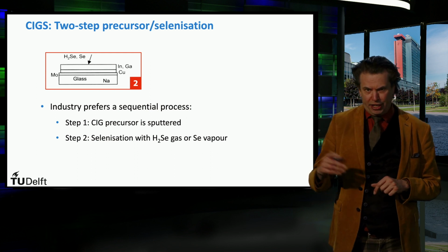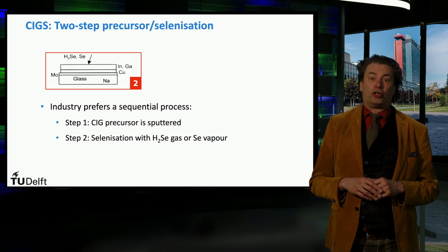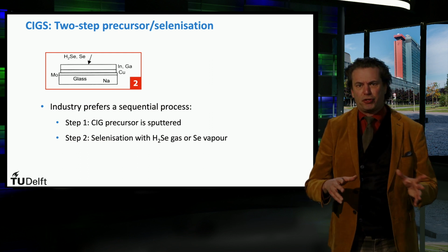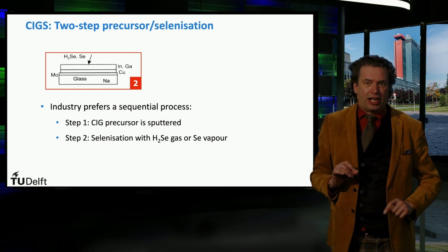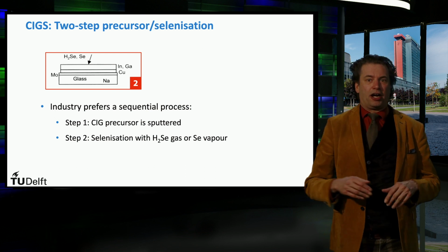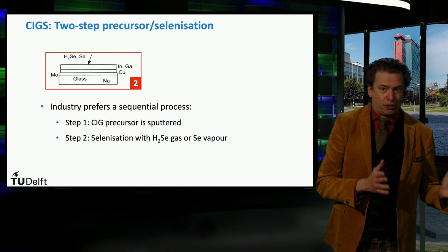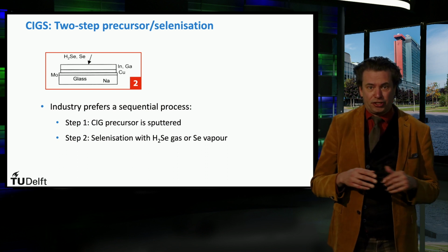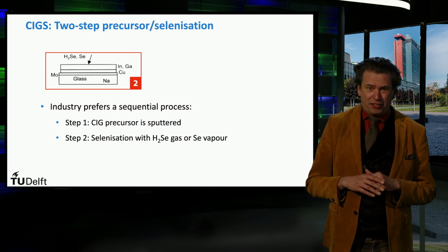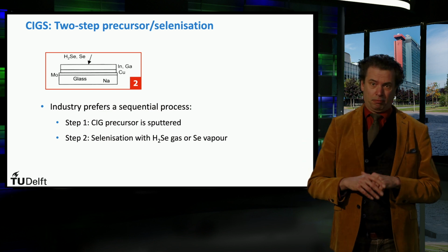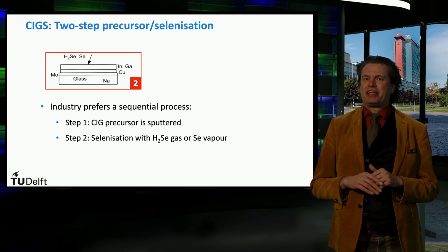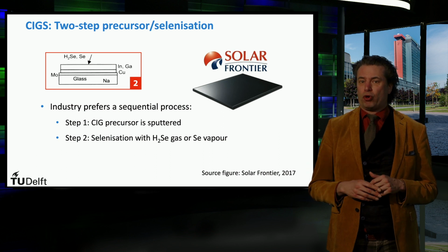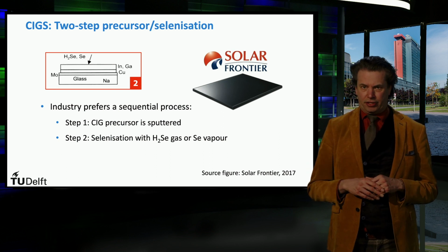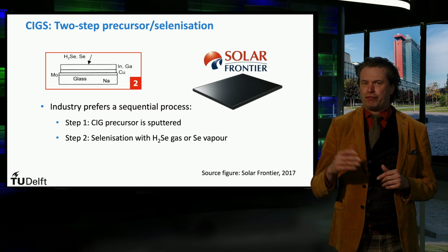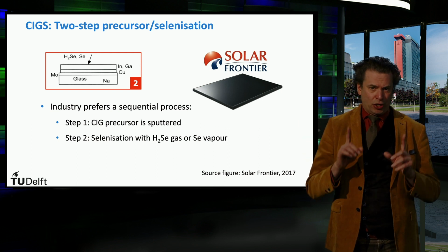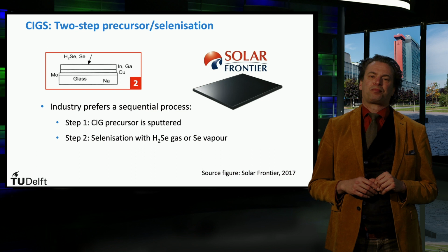selenization process. Here, a copper indium gallium, or CIG, layer is deposited on the substrate as a first step, while the selenium atoms are included in a selenization process with hydrogen selenide gas, which is very toxic, or by selenium vapor. This method is adopted by the Japanese company Solar Frontier, a market leader in this field, and they have reached conversion efficiencies larger than 22% with this two-step process.